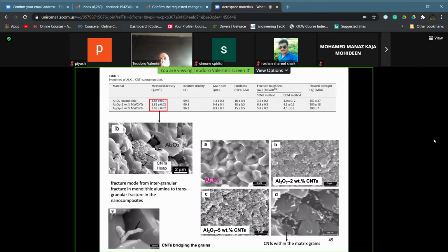So in the case of conventional composite materials, we are always in a situation in which the percent volume of the reinforcement is higher than 15%. Because what does the critical volume mean? The critical volume was the volume of the reinforcement under which we get no reinforcement of the matrix. If in conventional composite materials we use a percent volume of fibers lower than the critical volume, the mechanical resistance of the composite is lower than the value of the matrix considered alone. So it makes no sense to put fibers inside. And we are talking, in the conventional case, of critical values of about 15%.